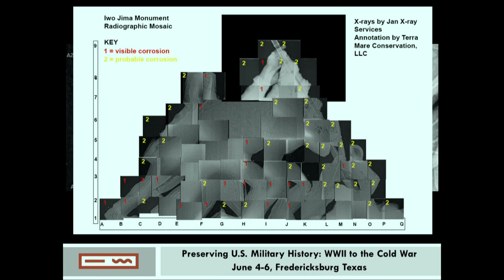We created this X-ray map to visually indicate where we thought the sculpture had to be opened up for treatment. And as I just explained, the red squares are high priority. The yellow was less high priority, but still problematic. Ultimately, 71 areas were opened up. Based on these results, a major restoration campaign was undertaken in 2015 to 2016 to stabilise the sculpture.